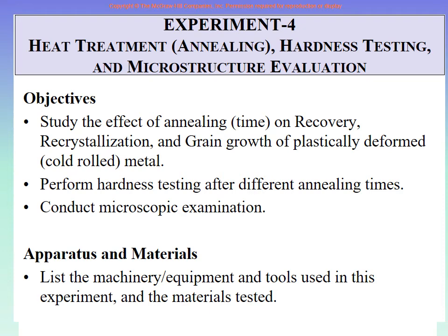When you do the first annealing, say for 10 minutes or 5 minutes, whatever you will see in the video, and then you take it out, then before you do the microstructure, you also go to the hardness machine and take 3-4 readings, to see what the hardness value was after the first annealing. So therefore you do the heat treatment, you do the hardness, and you do the microstructure.